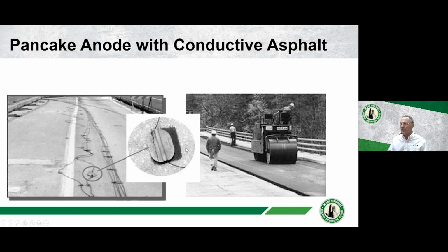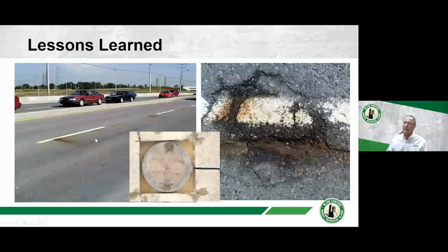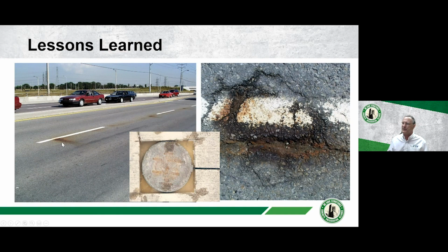Well, that worked out well until they milled the overlay up and ripped up all these wires, or you've run the system too hot, and the anode itself starts to corrode and cause a pothole at each one of these locations where an anode was. There would be a pothole there. The asphalt would blow up like this.